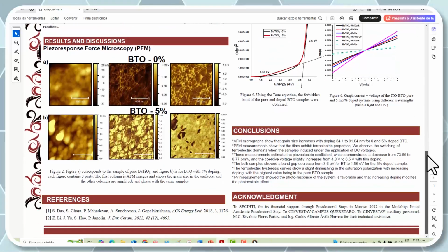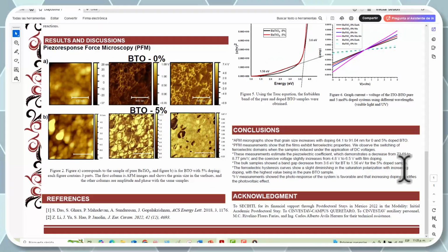Now, in the conclusion part, we found that the PFM micrographs show that the grain size increases with the doping. The PFM measurements show the films exhibit ferroelectric properties. This measurement estimates the piezoelectric coefficients, which demonstrate a decrease from the value of the bulk BTO.